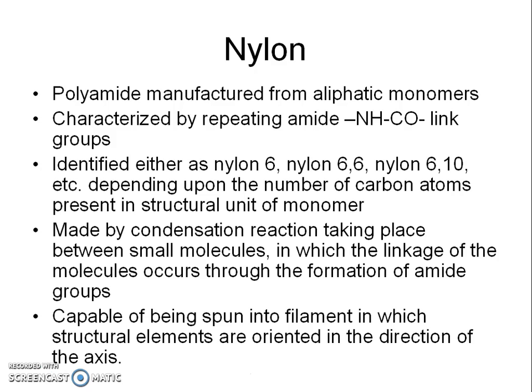Nylon is a polyamide manufactured from aliphatic monomers. It is characterized by a repeating amide group, i.e., -NH-CO- linkage. Nylons are identified as Nylon-6, Nylon-66, Nylon-610, etc., depending upon the number of carbon atoms present in the structural unit of the monomer. It is produced by condensation reaction taking place between small molecules, in which the linkage of the molecules occurs through the formation of amide groups.